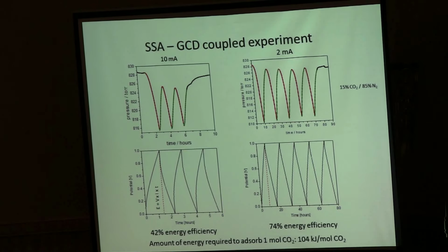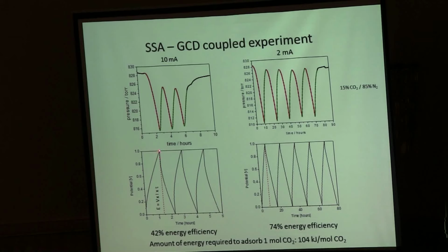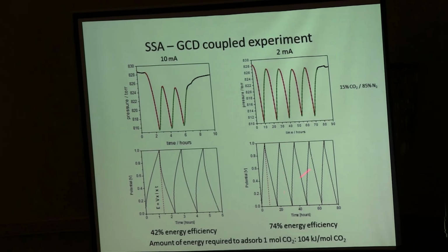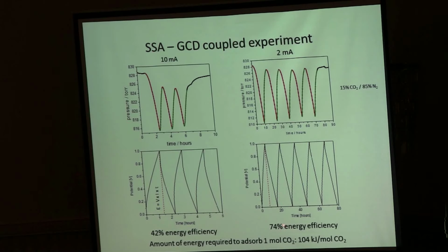Now what you can also do is calculate the area underneath the discharge curve, multiply it with the current, and that gives you the energy that you actually regenerate when you discharge. That gives you a charge discharge efficiency, which at 10 milliamperes is about 42%. When you charge at a smaller current, you see that the charge discharge curves become more symmetrical and your energy efficiency goes up to 74%.